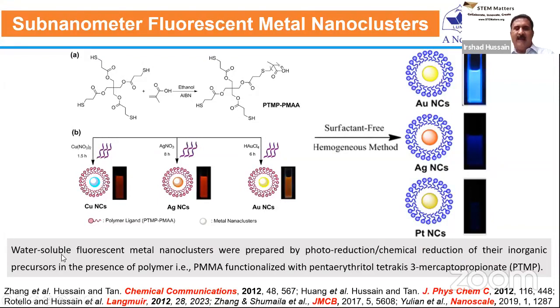So as I mentioned, you can control the size of these nanoparticles by controlling the nature of the ligand or stabilizer that you are using. And we know that thiol is one of the strongest capping agents for metals because it has strong affinity for metals, especially gold, silver and copper. So for this purpose, in collaboration with our Chinese collaborators, especially Professor Tang Bian, we designed polymers which have multiple free thiol functional groups.